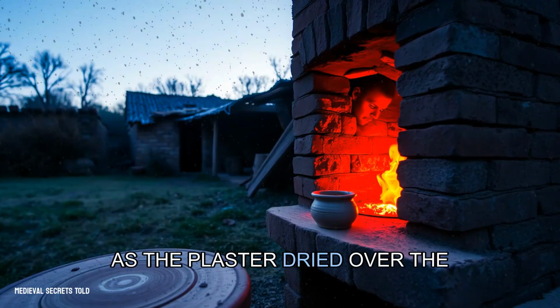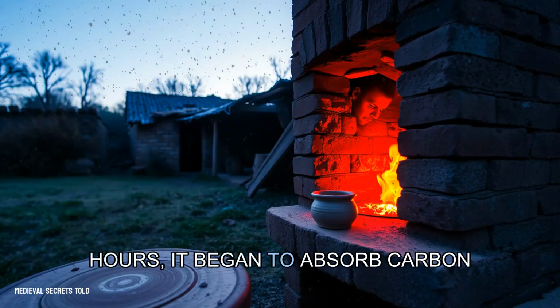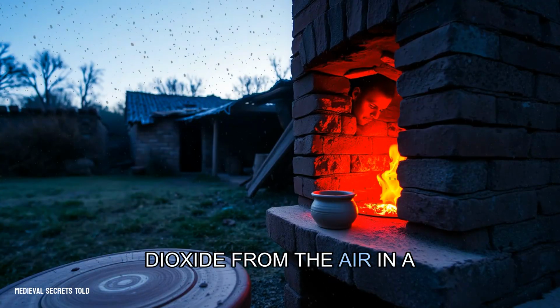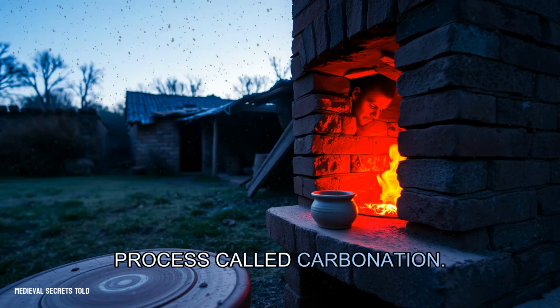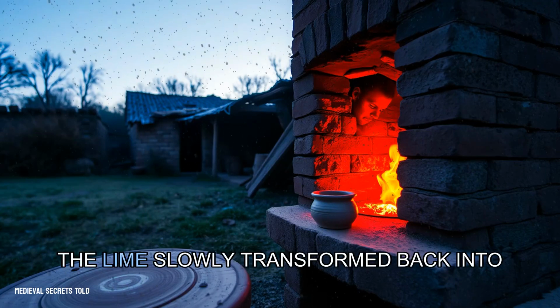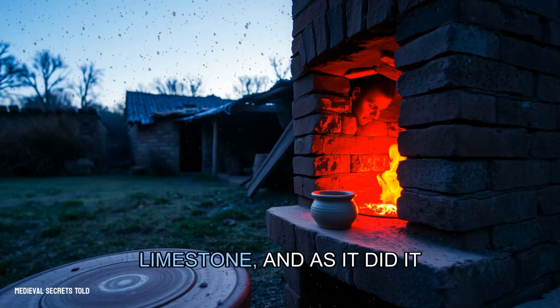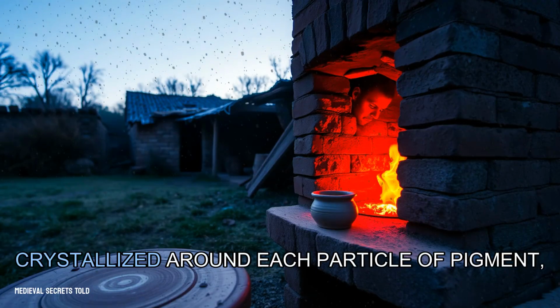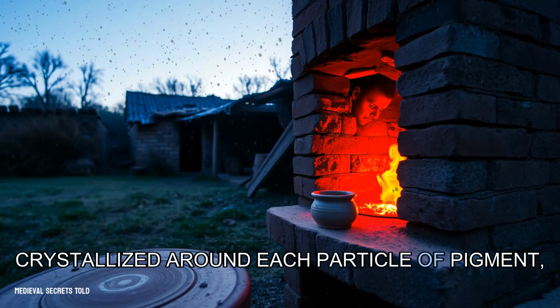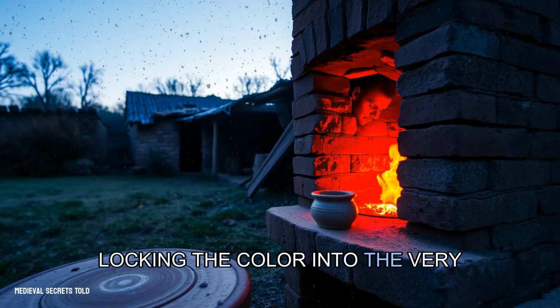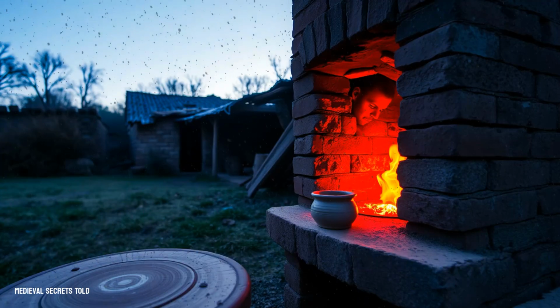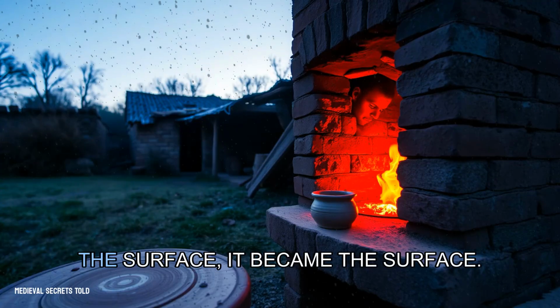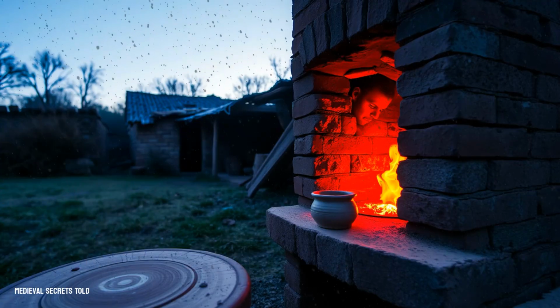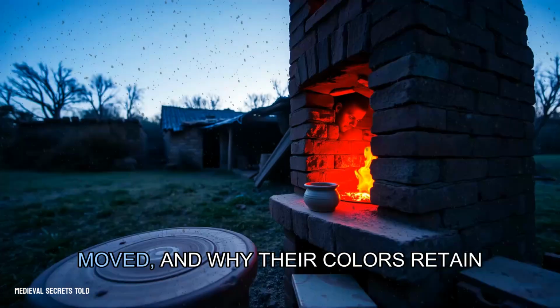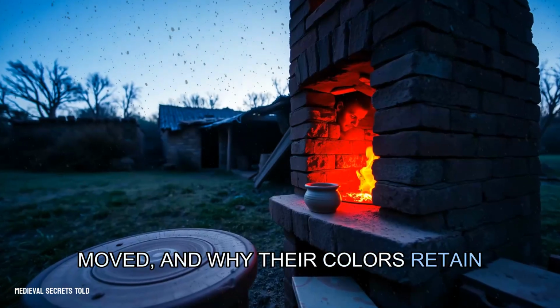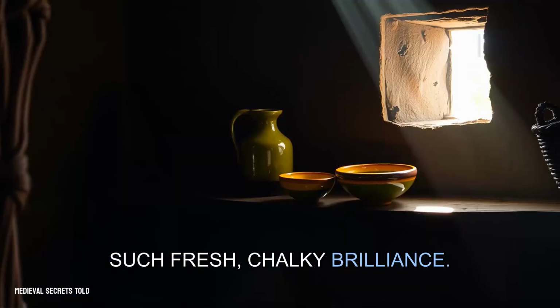As the plaster dried over the hours, it began to absorb carbon dioxide from the air in a process called carbonation. The lime slowly transformed back into limestone, and as it did, it crystallized around each particle of pigment, locking the color into the very fabric of the wall. The painting did not sit on the surface, it became the surface. This is why frescoes cannot be moved, and why their colors retain such fresh, chalky brilliance.